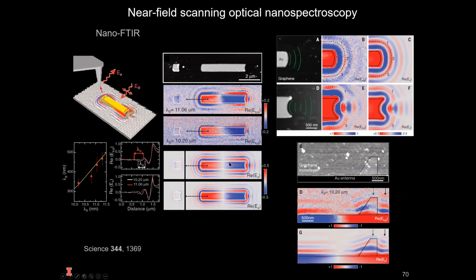In those works, the authors were able to detect the focusing of the plasmon by the specially shaped antenna, and the refraction of those plasmons caused by a thicker flake of the graphene on the sample.